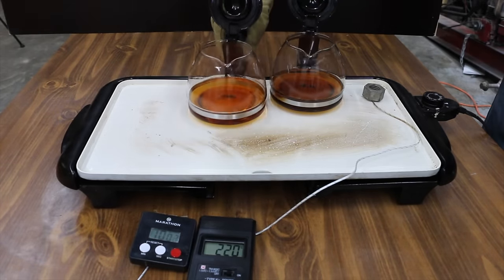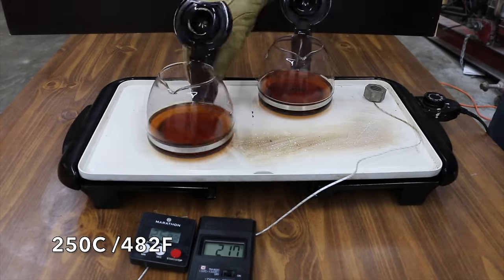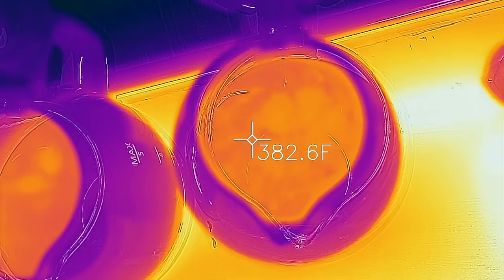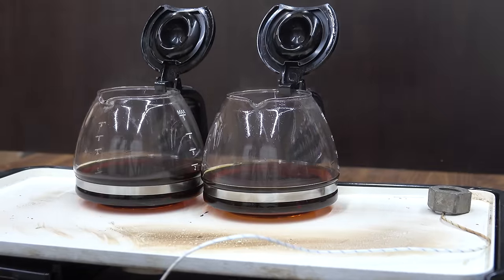The appropriate test to measure evaporative loss is known as the NOACK volatility test, which exposes oil to 482 degrees Fahrenheit for 1 hour to simulate conditions in and around the top of piston rings of engines. So what happens when oil vaporizes excessively? It becomes thicker and heavier, contributing to poor oil circulation, reduced fuel economy, increased oil consumption, wear and emissions.